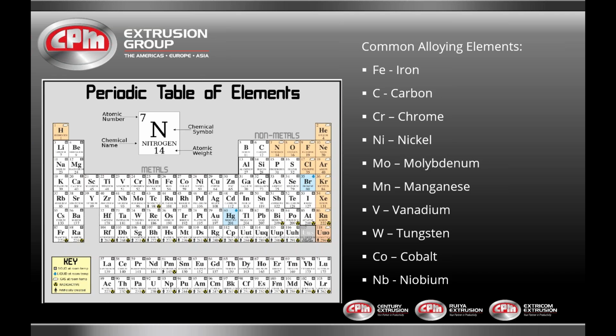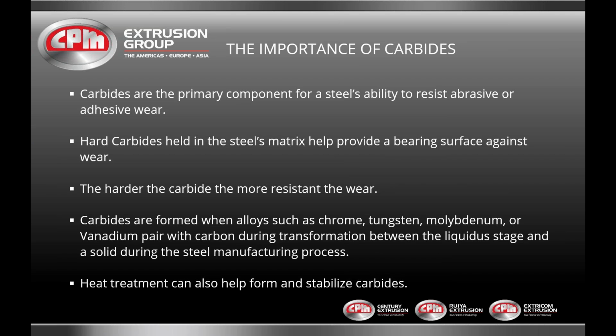Carbides are the primary component for a steel's ability to provide wear resistance. The hard carbides held in the steel's matrix provide a bearing surface against wear. The harder the carbide, the greater the wear resistance. Carbides are formed when alloys such as chrome, tungsten, molybdenum, or vanadium pair with carbon during the transformation between the liquidus stage and solid during the steel manufacturing process. Heat treatment can also help form and stabilize carbides.